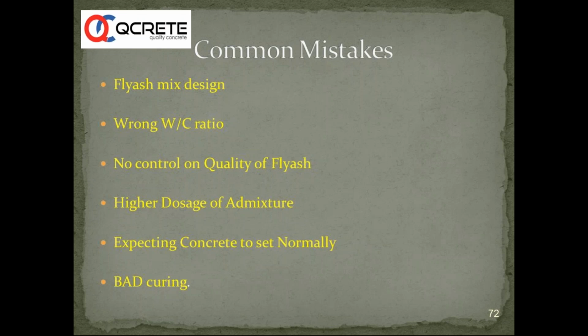In other countries like Europe, all these are specified. All the fly ash characteristics are guaranteed by the supplier. For example, in some European specifications they talk about different classes of fly ash. Category N, where the retention is less than 40% on 45 microns, and another category S, where the retention is less than or equal to 12% on 45 microns. Category S comes with guaranteed water reduction. So if a company is selling a fly ash having less than or equal to 12% retention on 45 microns, it comes with guaranteed water reduction.